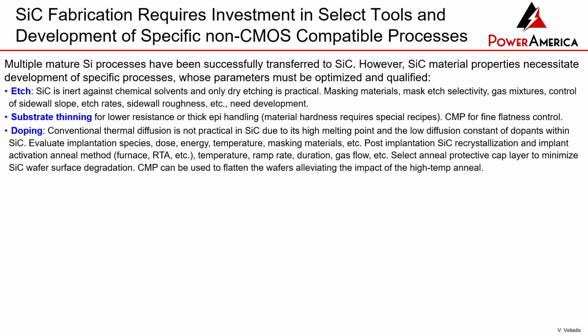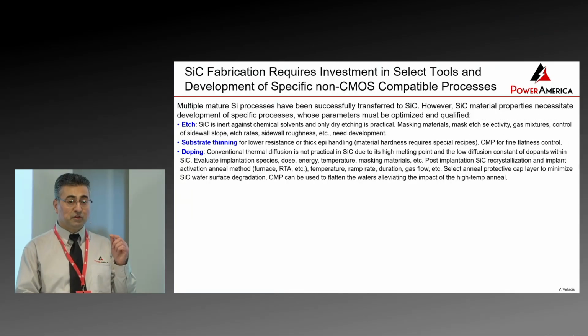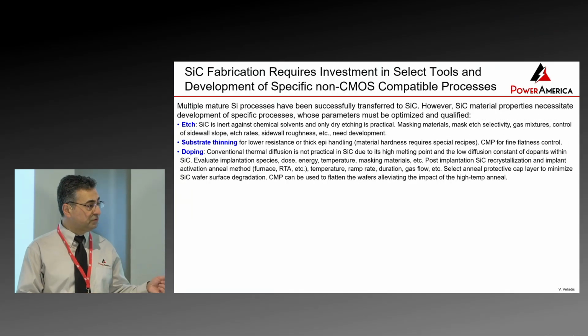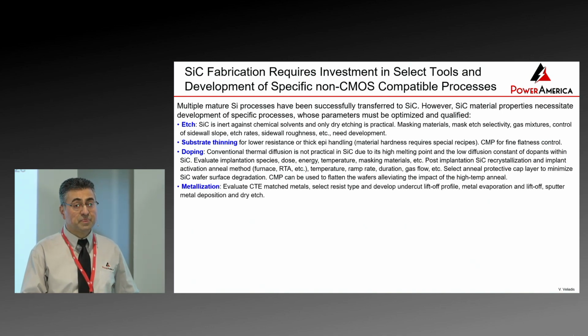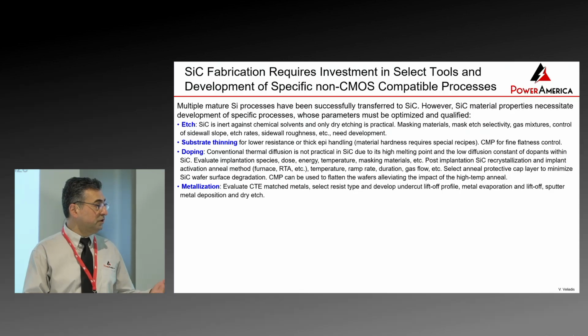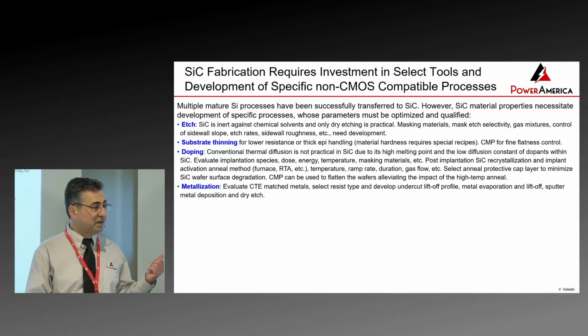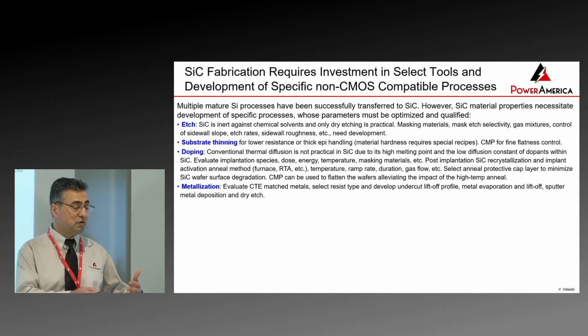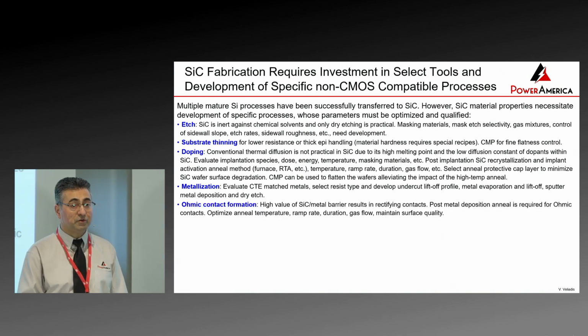Doping, okay? You need to have heated implantation, and even that's not good enough. Then you need to do an anneal to activate the dopants and recrystallize the wafer. Metallization, you need to have CTE matched materials, so things like tungsten, molybdenum, titanium tungsten, those are good materials, and you need to know how to put them in your device.